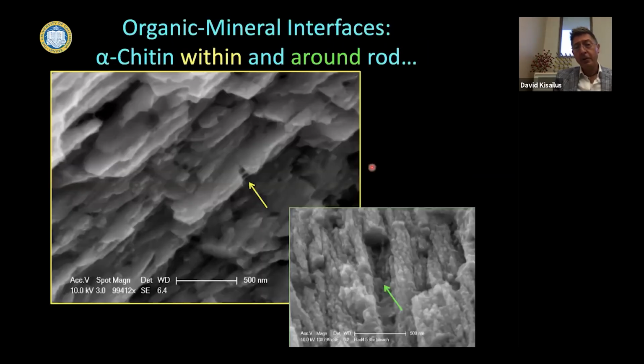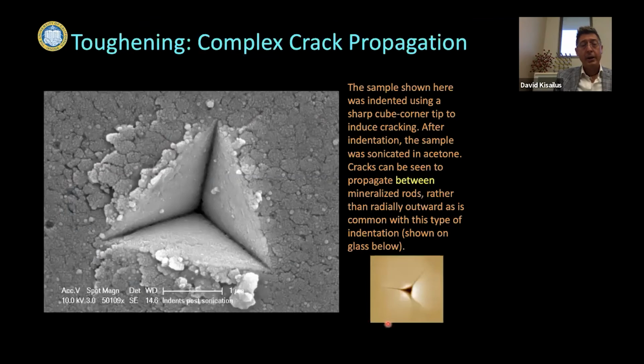And we took a closer look at those mineralized magnetite nanorods. You can actually see some organic fibrils that form a veneer around. Here's a region where one of the nanorods pulled out. You can actually see this organic veneer that surrounds these nanorods. And this is alpha chitin, a polysaccharide.